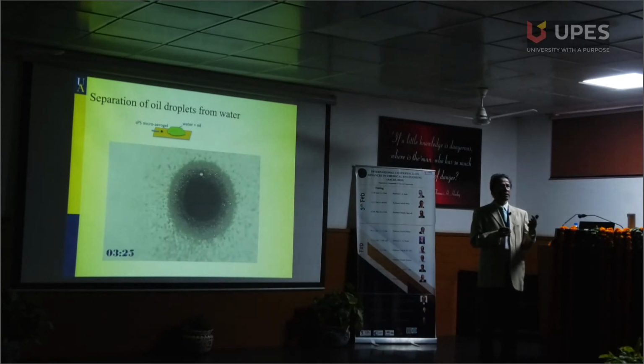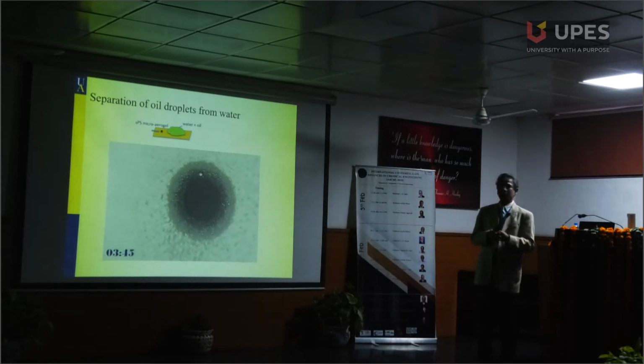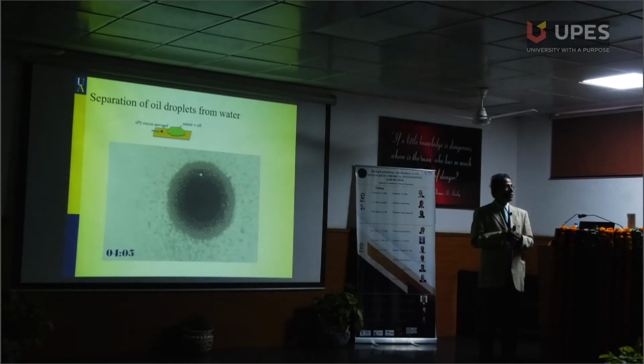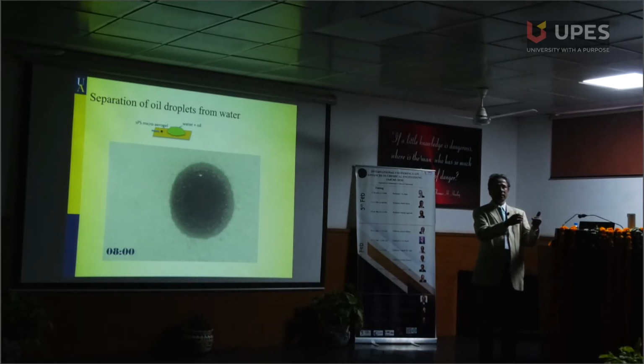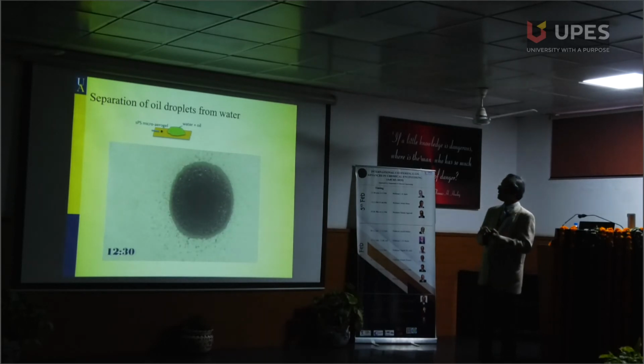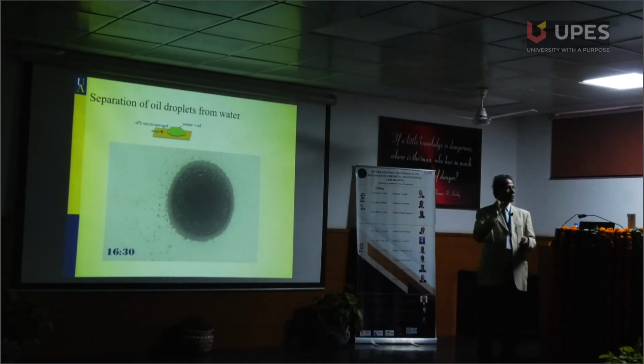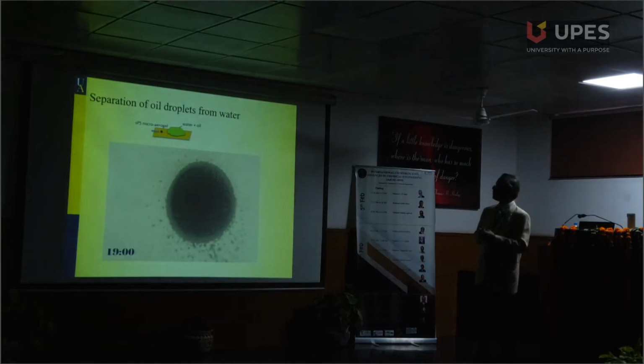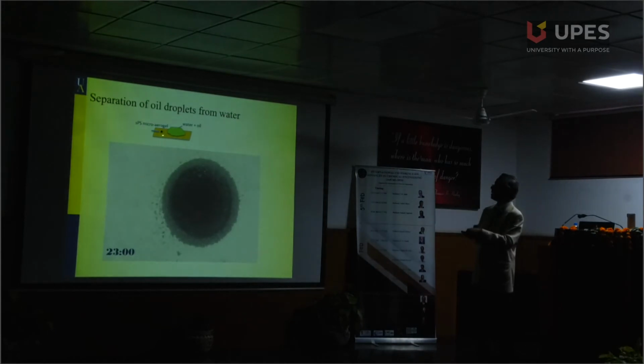There is a variation of polystyrene which is syndiotactic, which is more pricey, and that material can undergo thermoreversible gelation. You can dissolve it in a hot solvent, and as you cool down, the material turns into a gel. So we converted that polymer solution into tiny droplets, and each droplet turned into a micrometer-size particle like here.